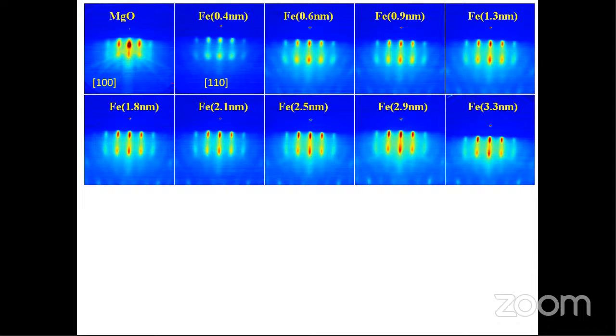That's why the blurred nature of the spots. As the film thickness increases, the blurred spots convert to a sharp, elongated spotty pattern. After 2.5 nanometer thickness, the elongated spotty patterns touch each other and a modulated streaky pattern is observed. One thing to note is that no extra spot has been observed between the two modulated streaky patterns,